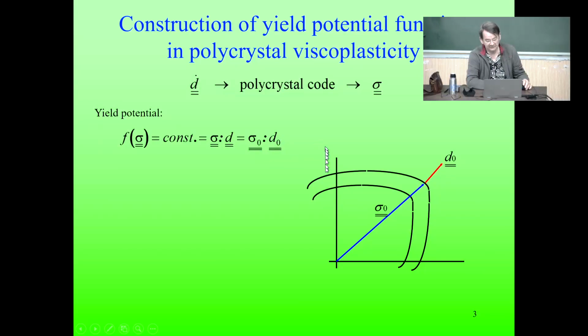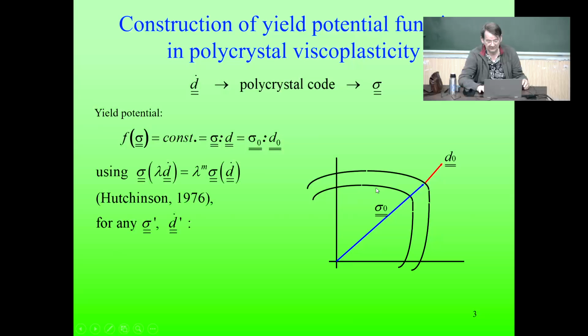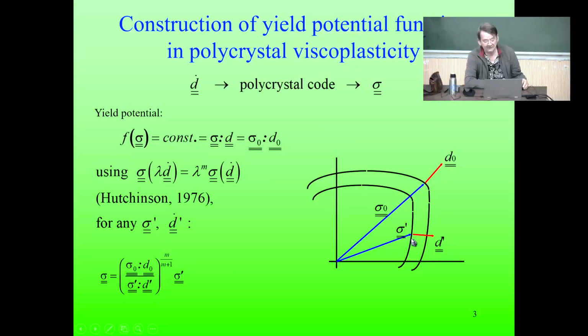So all along here, you see there are two different yield potentials shown. They are similar in shape if there is isotropic behavior. Anyway, they are similar in shape if we only change the strain rate. But what is happening is that if we are at a given stress level sigma prime, by increasing the strain rate, we are going to jump onto another yield potential. These are equipotential functions, and they are defined like this. So the plastic power is constant along them.